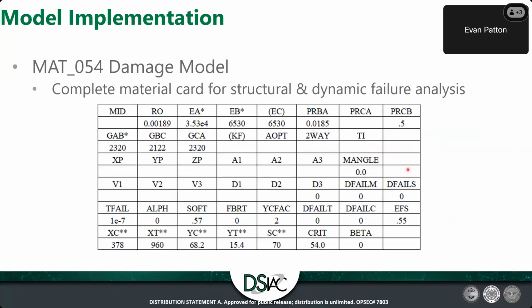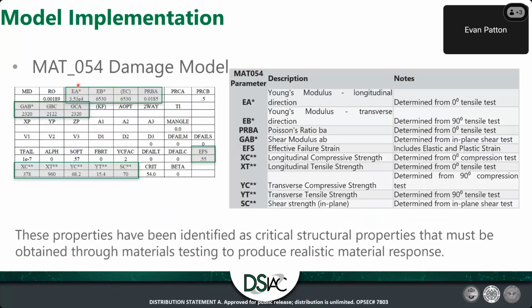When we input our mechanical characterization data, this is what we input into the system. Those gray boxes highlight everything that we experimentally derived. Everything else is either a geometric property that tells LS-Dyna which way the fibers are going, or parameters like these that determine how the model accumulates damage and tune your model to what you see experimentally. So this model is essentially a representative model instead of a predictive model, although it can get you close if you're familiar with the material and its behaviors.